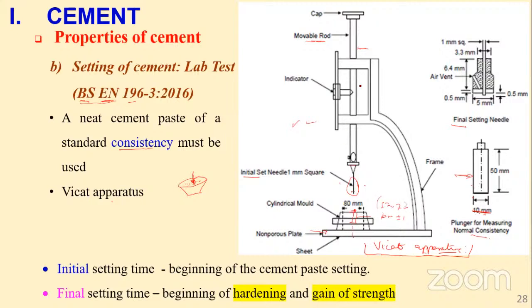Just to clarify something, on this part that we are not seeing, we have shown a profile, a cross section. If you look from this direction, there is a gauge you can read here to see the readings. So you can see the penetration. When it's resting on the surface here, you see the zero reading. Then when you release a knob here, and it moves down, you see the penetration in your cement paste. If it's between 5 to 7 millimeters, we say that the cement paste is of standard consistency.